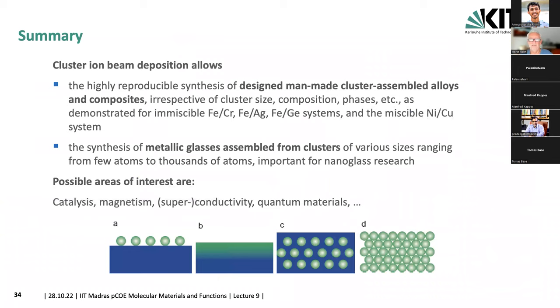So my summary, and with that, I'm at the end. I wanted to show you that cluster ion beam deposition allows the highly reproducible synthesis of designed man-made cluster-assembled alloys and composites. And this can be done irrespective of cluster size, composition, phases, and so on, as we have demonstrated for immiscible and miscible systems. But we can also go towards metallic glasses, which are assembled from amorphous clusters of various sizes. And we can maybe get new metallic glass structures, which we have not seen by other methods.